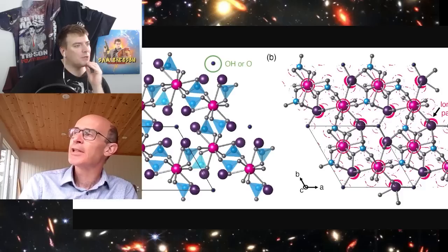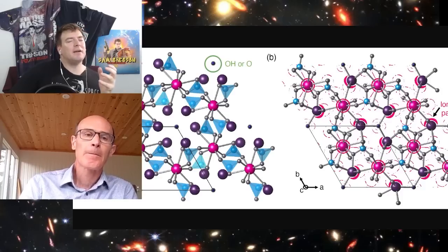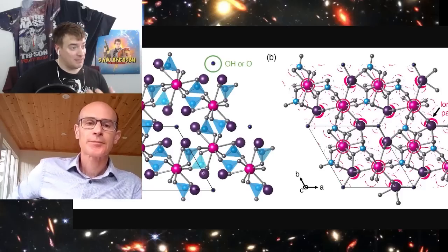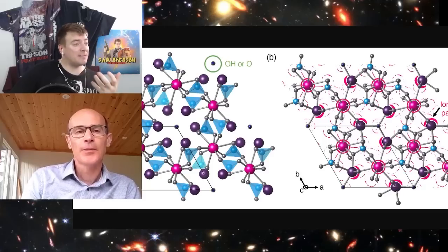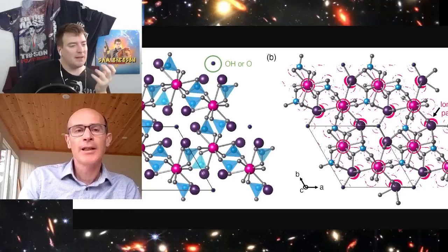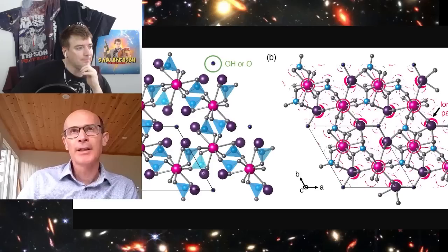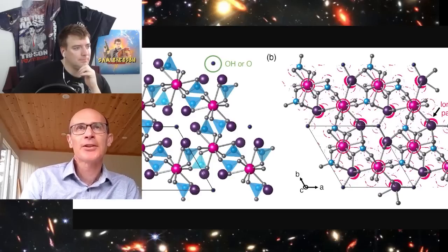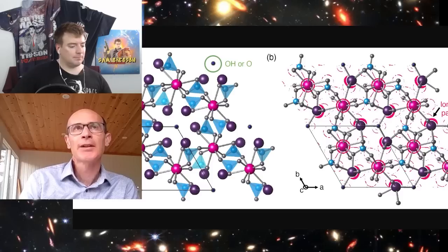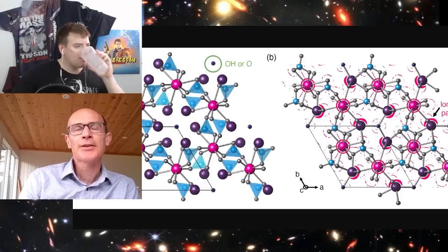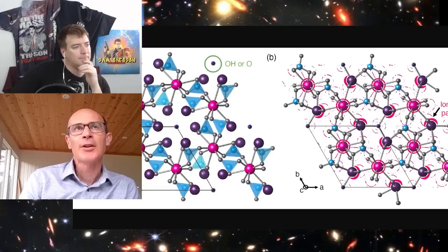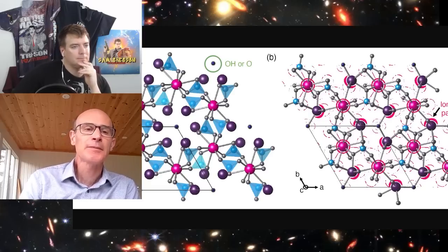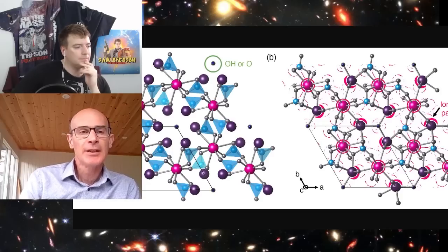So it's not disqualifying that experts might not expect this to be superconducting. It still could be. It's not 100% disqualifying, but it would be surprising. In the apatite case, I think it would be very surprising, partly because the amount of the transition metal copper is rather small. In the copper oxide superconductors, they're much richer in copper, and the coppers are in fairly close proximity.